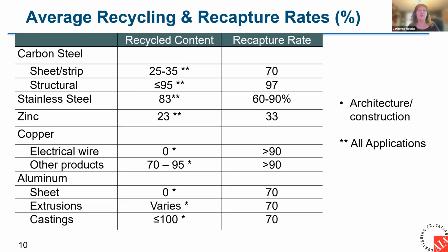I did promise to provide some comparison of stainless steel with other architectural metals. As you can see, I put in the 83% recycled content for the United States and showed there were a 60 to 90% recapture rate that was shown on the prior slide. In comparison with carbon steel, it really depends on the type of product as to how much recycled content it will contain and what its recapture rate is. It is a lower value material. The large structural sections can also have a lot of recycled content, and they're very easy to capture and recycle. Well, sheet and strip may be limited to 25 to 35% recycled content. It really depends on the technology that's being used.